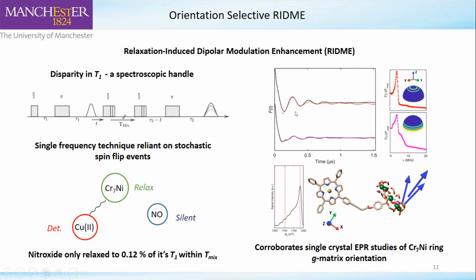And we get these nice RIDME traces. Obviously we're doing an orientational analysis of this, so we could look at both the gxy component of the copper and the gz component of the copper. And you can see that when we're looking at the gxy, which is the pink trace here, we get these higher frequency contributions to the trace, which we don't see in